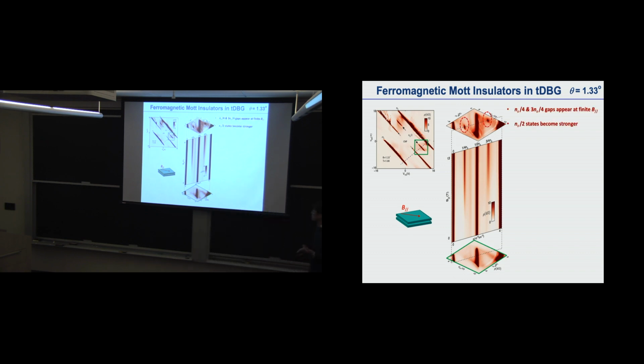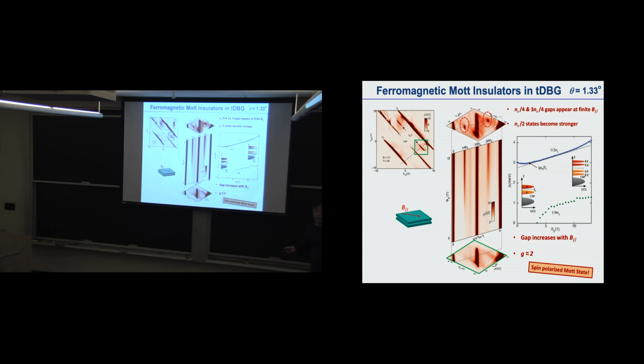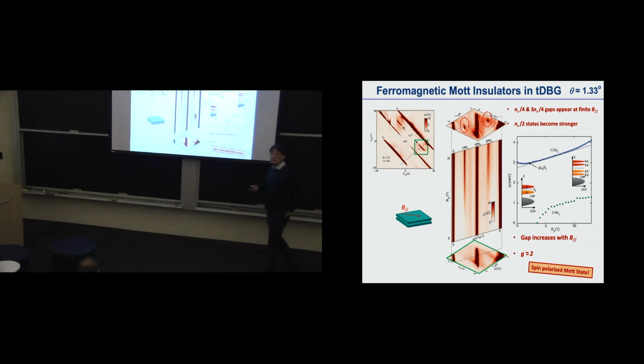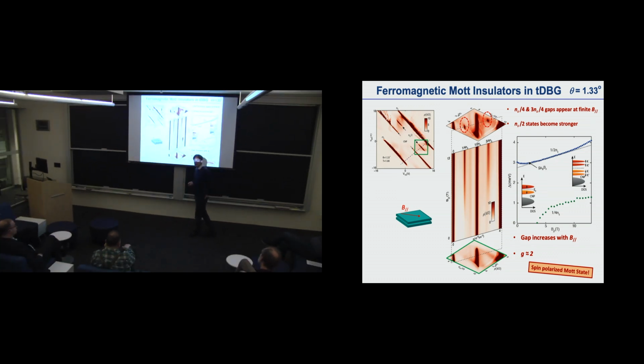You can do a little better job by looking at all the temperature dependence and plotting out the gap. It turns out the gap is increasing with the in-plane magnetic field. That's completely opposite to what we saw in the single layer case. The naive interpretation is that each of these correlated states or Mott states is spin polarized, such that increasing the magnetic field causes Zeeman splitting that increases the gap. Indeed, the slope we measured is more or less tied with this Zeeman gap increase, so we know this strongly suggests spin polarized Mott states, or ferromagnets if you want to say.